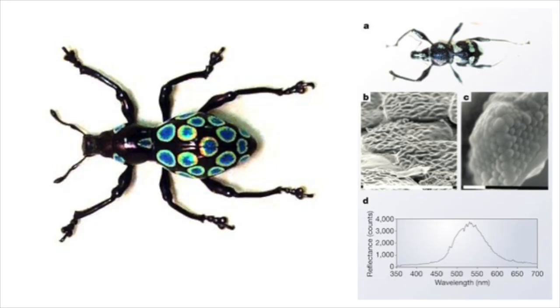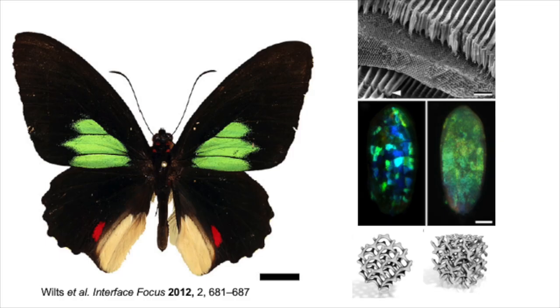The visual appearance of the butterfly P. sesostris is particularly striking. While the overall color of the upper wing surface is jet black due to highly melanized scales, large green spots dominate the forewings and smaller red spots mark the hind wings. These colored regions arise from photonic crystals composed of assemblies with a gyroid-type morphology, with a chitin filling fraction of about 30 to 40% and a cubic unit cell size in the range of 280 to 330 nanometers. The photonic crystals are overlaid by a thick lamellar structure known as a honeycomb.